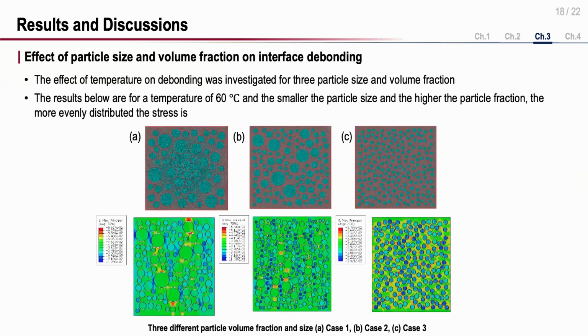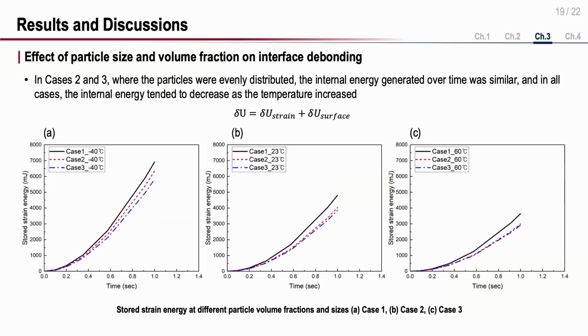And the last case is the effect of particle size and volume fraction on interface debonding. It was found that the smaller the particle size and the higher the particle fraction, the more evenly distributed the stresses and the less debonding. In cases 2 and 3, where particles were evenly distributed, the internal energy generated over time was similar. And in all cases, the internal energy tended to decrease as the temperature increased.